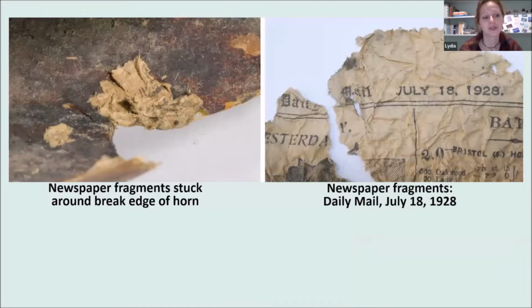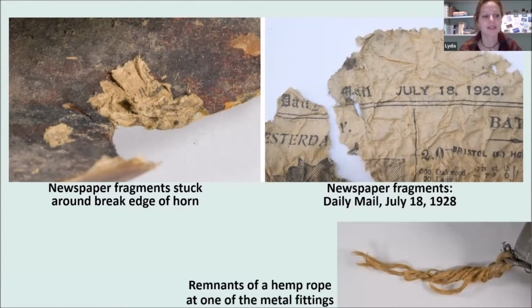In the end, we could not find out when exactly the horn broke into two pieces, but I could identify on behalf of newspaper fragments, which were trapped in between horn and the bandages, that it had been mended in 1928. Due to this information, we assume that the damage occurred early 1900 and that the hemp rope used for hanging the horn onto a wall simply failed, so that the horn fell onto a hard surface where it broke into two pieces.